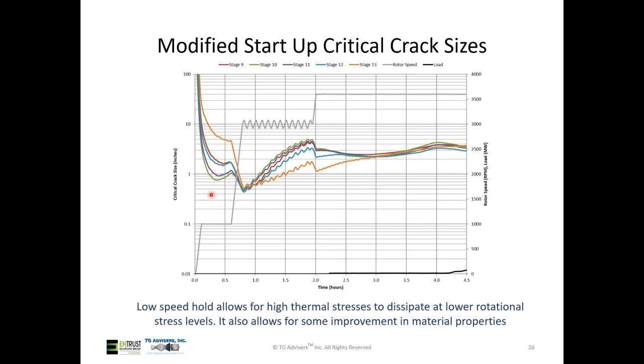Now, we certainly could make up for this time elsewhere, right? Like reducing the pre-warm or reducing that back end, the loading time when we've got good ductility, better material properties. So giving a little bit in this phase 2, run up the speed, I can get it back elsewhere and end up with a safer startup, but also end up with a faster startup still. So the low speed hold allows for high thermal stresses to dissipate or reduce at lower rotational stress levels. It also allows for some improvement in material properties.